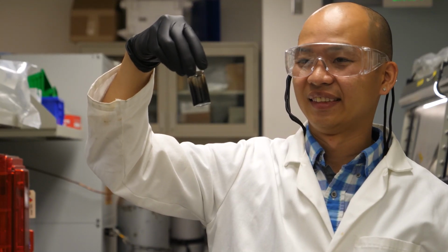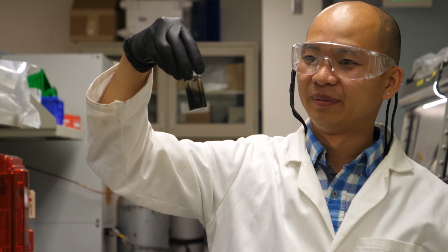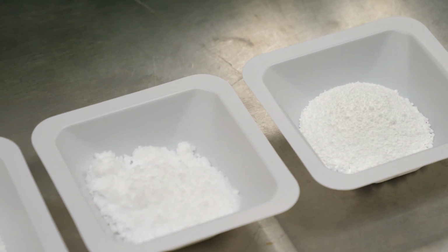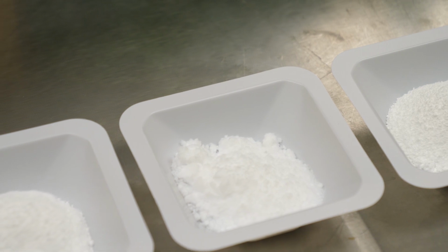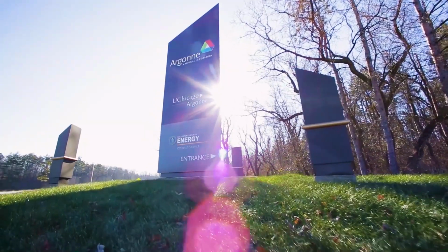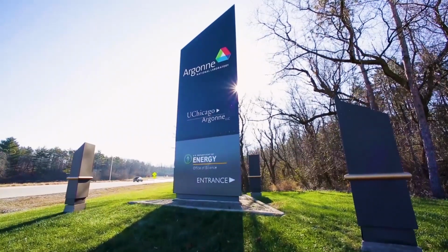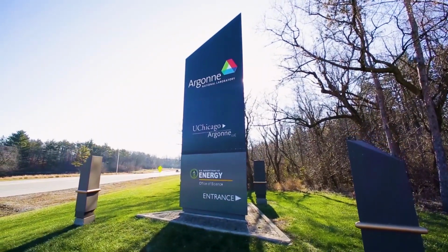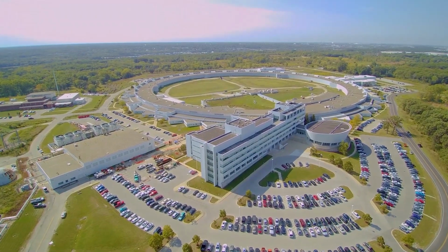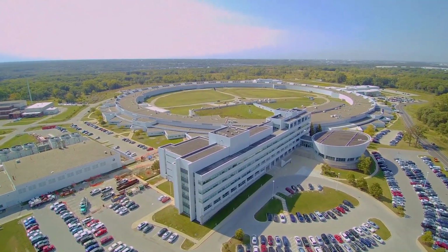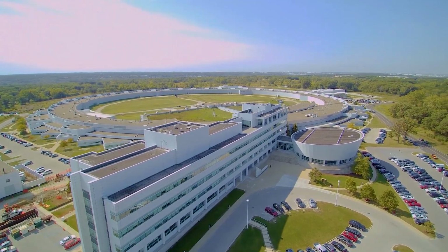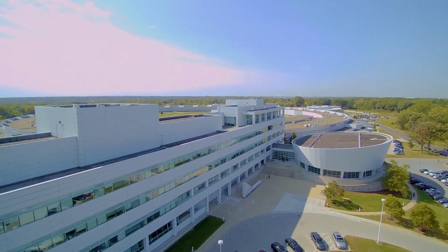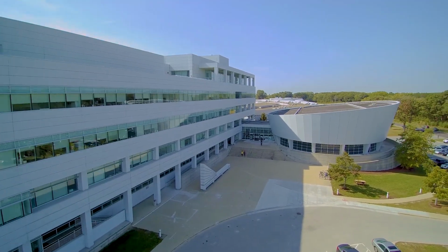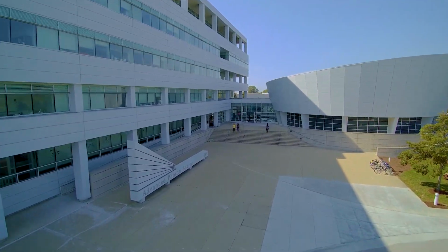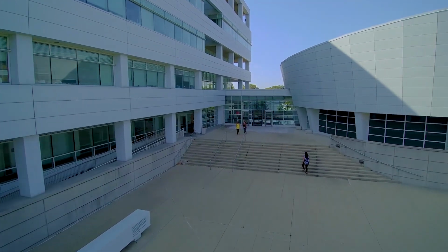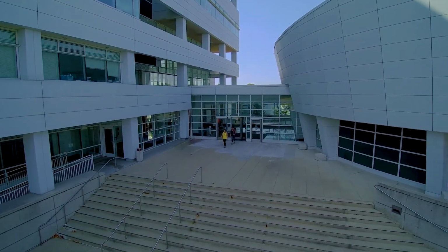Some of the metal carbide nanoparticles that we make are in the single nanometer range, such as 2 to 4 nanometers. We can support these particles on different metal oxides or carbons to give us catalysts with very high active surface areas. Characterization plays a critical role in all aspects of catalyst development. During the early stages of the cycle, we seek feedback on how effectively we've been able to translate computationally predicted attributes into a model catalyst system so that we can rapidly iterate on catalyst synthesis. As the development cycle progresses, our focus shifts to the evolution of the catalyst structures under realistic pretreatment, reaction, and regeneration conditions so that we can accurately describe and improve upon the real working catalyst system.